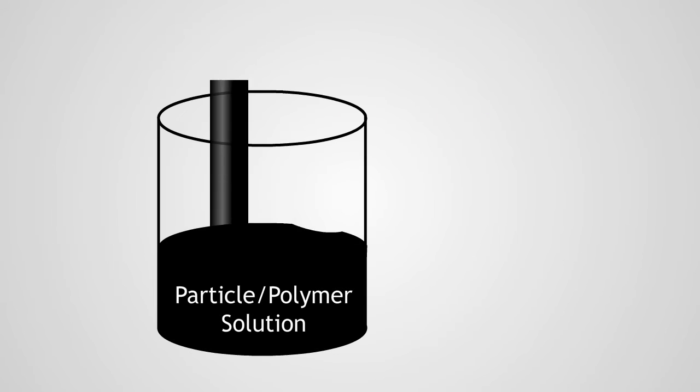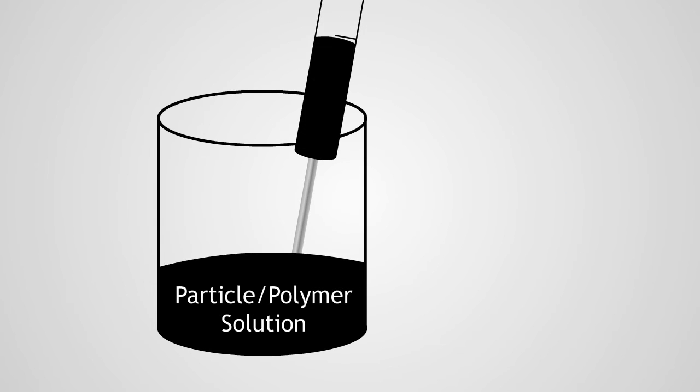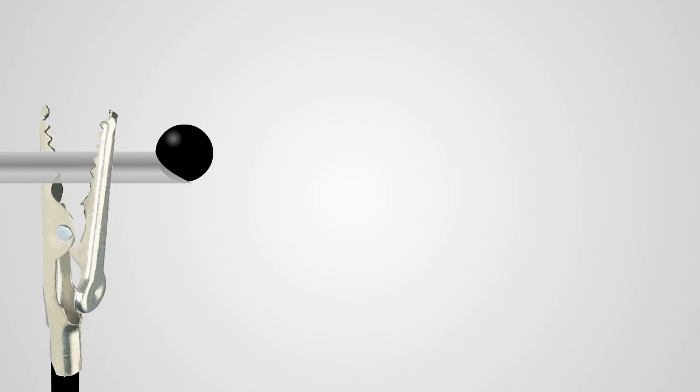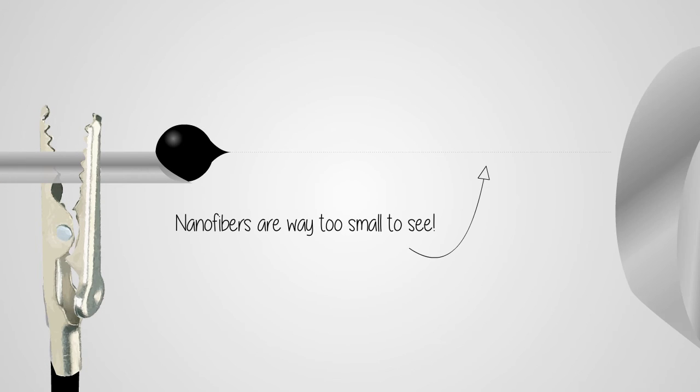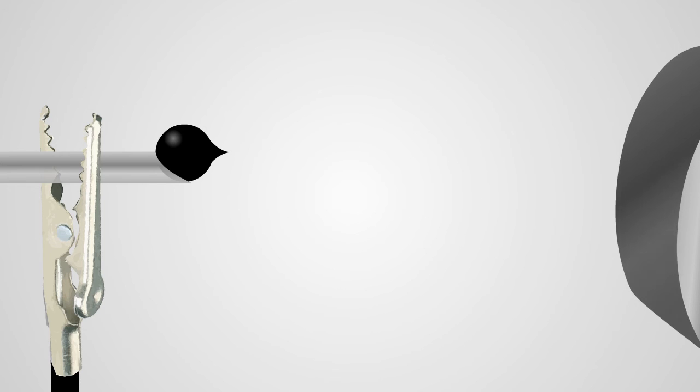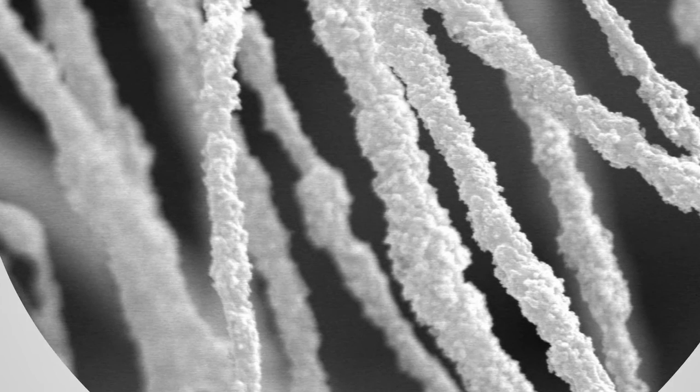The way I do this is by utilizing a technique called electrospinning. Electrospinning involves subjecting a droplet of polymer solution to a strong electric field. This field overcomes the surface tension of the droplet to form nanofiber. Over a period of time, these nanofibers collect to form a 3D structured mat, which I can use as a fuel cell electrode.